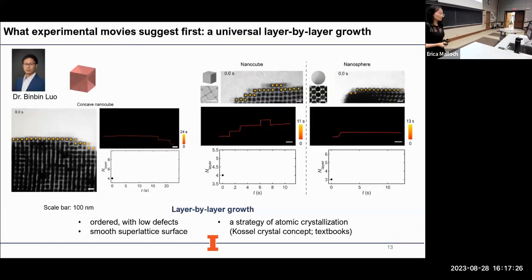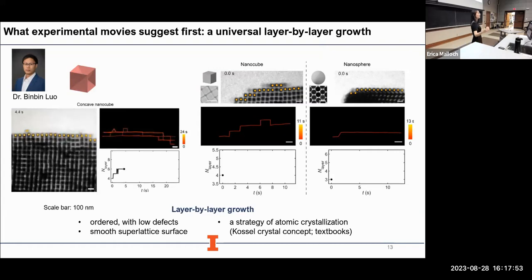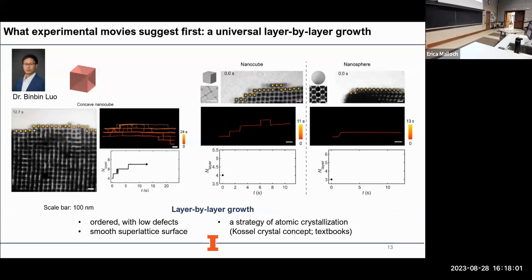My former PhD student, Binbin, was able to substantially upgrade our liquid phase TEM imaging protocol so that we can now observe the growth of large three-dimensional crystals. Binbin also developed and synthesized a series of differently shaped particles, the concave cubes, the flat cubes, and nanospheres for comparison. So let's look at the movies one by one. In the first movie, you can already see the crystal has grown pretty big, so it's definitely post-nucleation. If you look at the growth front, the incoming particles will only complete one layer before growing another layer. There are actually no random fluctuations.